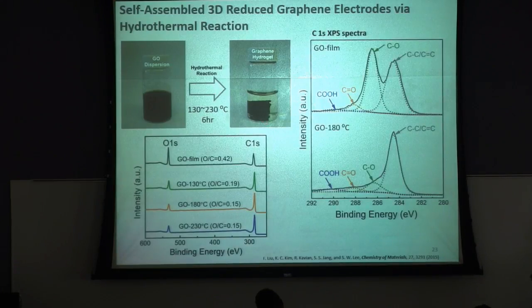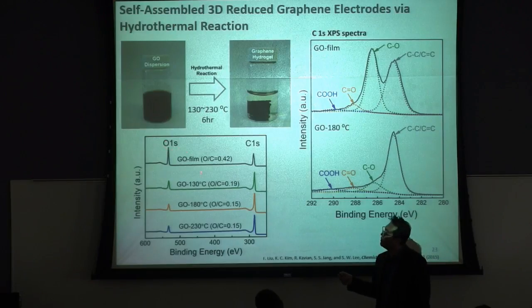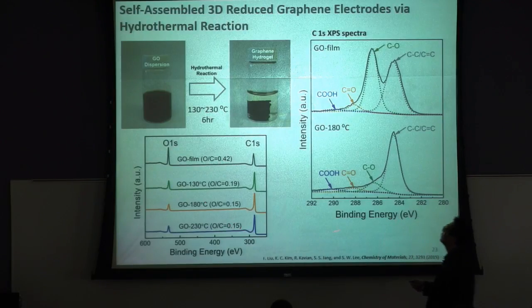If we look at the surface chemistry, graphene oxide has a high oxygen to carbon ratio, 0.42. If we simply increase the hydrothermal reduction temperature, we can reduce this ratio to around 0.15. If we look at the high resolution XPS peaks, this graphene oxide film has dominant C-O peaks, coming from the hydroxyl or epoxide groups. But after hydrothermal reduction, we can see a huge decrease of this peak. Basically, this indicates the recovery of the sp2 conjugation network of graphene.